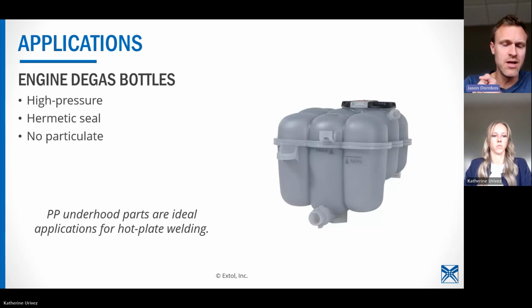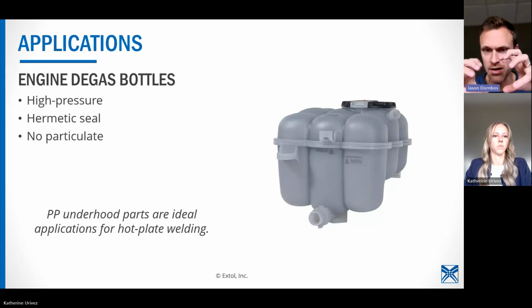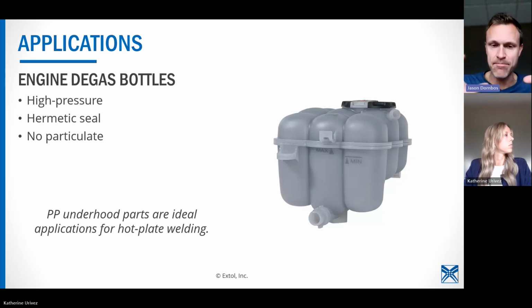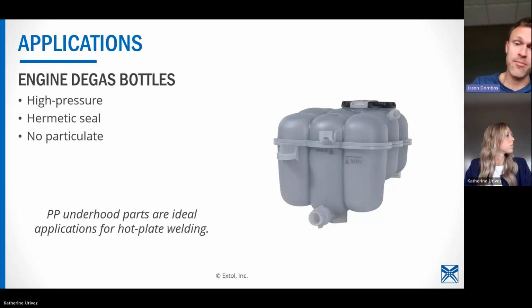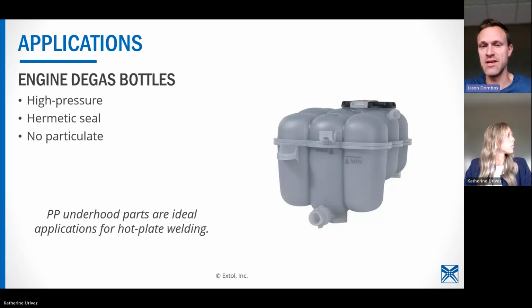It's a high pressure application. This is one where we almost always are doing a burst test. And when we burst test these, the part cracks and breaks open, but not at the weld. The weld itself achieves a better than parent material strength because the weld rib is made to be slightly wider than the actual wall thickness of the rest of the assembly. There's no particulate. These have to be clean, and there's a hermetic seal. So in general, this is an example of a polypropylene part that lives underneath the hood of an engine. There's lots of other polypropylene and other plastic materials inside of an engine of a car, and a lot of them are hot plate welded.